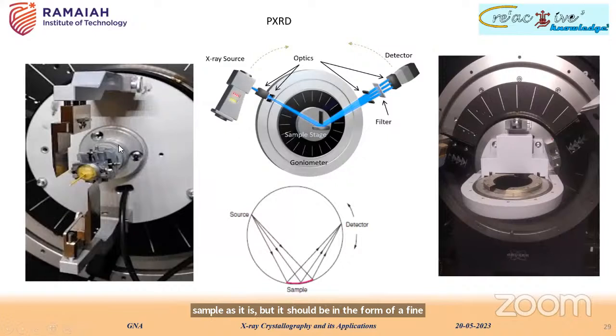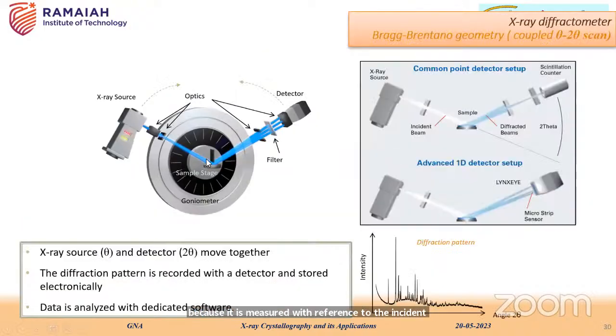In the powder diffraction technique, we place the powder in the sample holder in the goniometer, and we rotate both the X-ray tube and the detector. This scan is called coupled theta and 2 theta. The angle at which the X-ray source is moved is theta. The angle at which the detector is moved is actually 2 theta, because it is measured with reference to the incident beam.